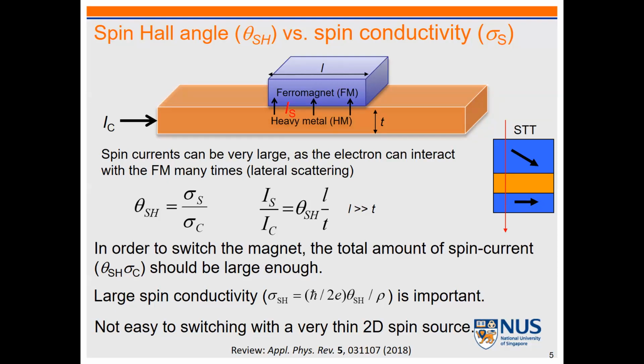And initially we were so excited. Oh, we need to find a large spin Hall angle because this is the efficiency of conversion. So then people tried to find all kinds of materials, including my group, and we found many materials. You can have a spin Hall angle of more than 100, no problem. But at the end, it's not useful because typically large spin Hall angle materials lead to very large resistivity. Okay? Because you need more scattering to generate more spin-dependent scattering. That will give you a large spin Hall angle. So eventually, the most important thing is this spin conductivity, which is defined by spin Hall angle divided by resistivity, or spin Hall angle multiplied by charge conductivity. So this is the most important attribute we need to look at. This is why many interesting 2D materials, for example topological ones, can have very large spin Hall angle, but eventually it's not very useful because they are very resistive, including many 2D materials.